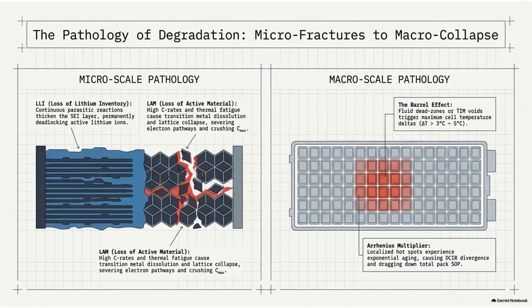Heat is the ultimate catalyst here. That single cell with the tiny TIM void undergoes rapid, localized loss of lithium inventory and loss of active material. Its direct current internal resistance, or DCIR, just spikes aggressively compared to its neighbors. Because the cells are wired in series, right? So this high-resistance hotspot becomes a massive bottleneck. Huge bottleneck. During heavy acceleration, that elevated internal resistance causes a severe voltage drop across that specific cell. And the BMS sees that.